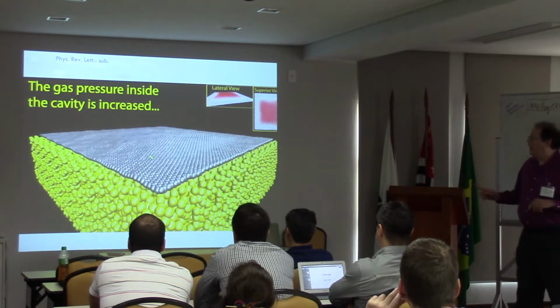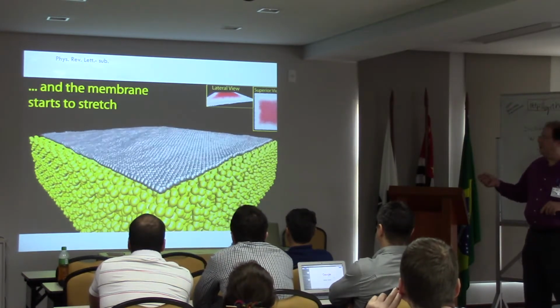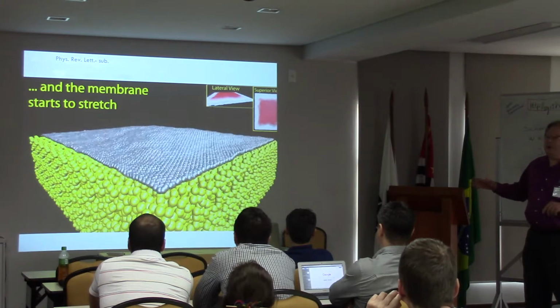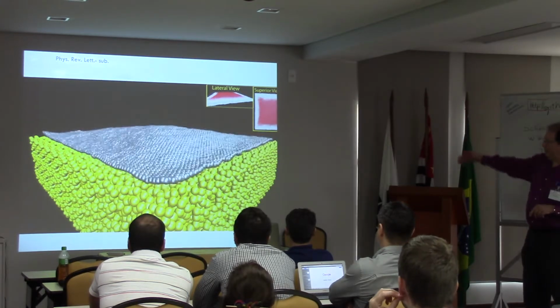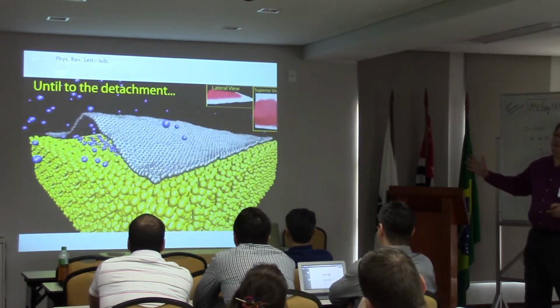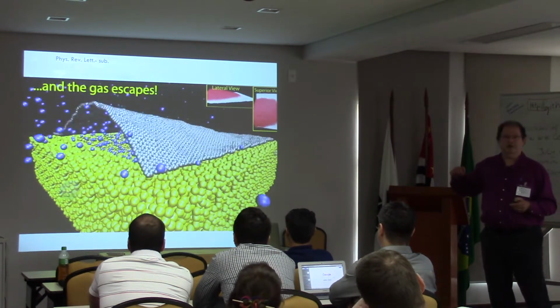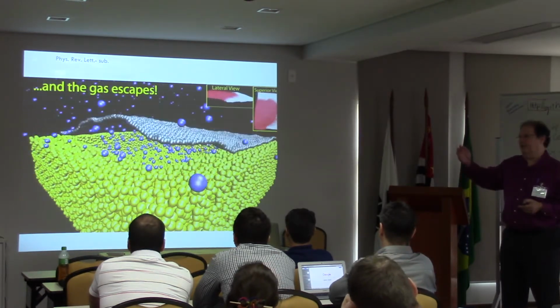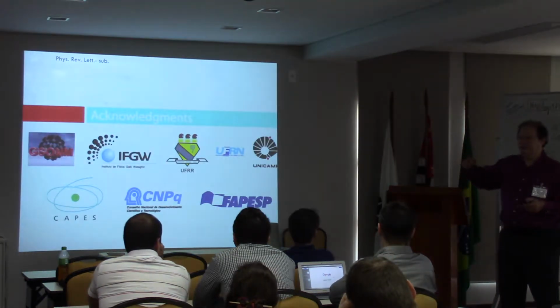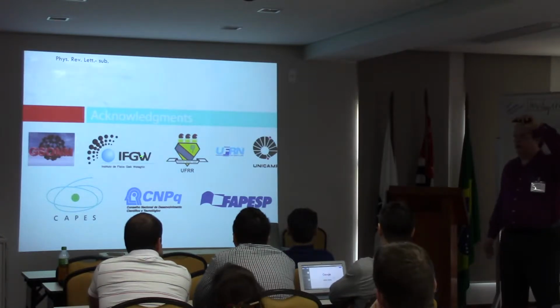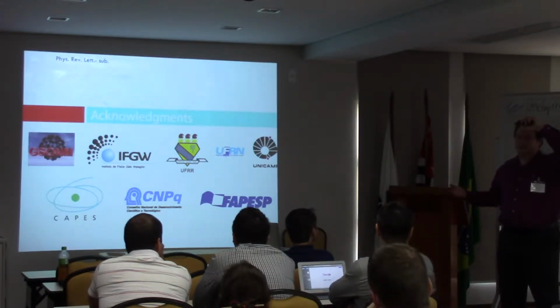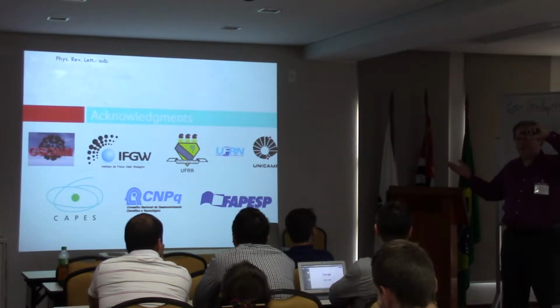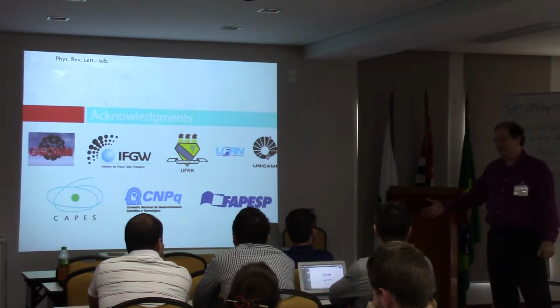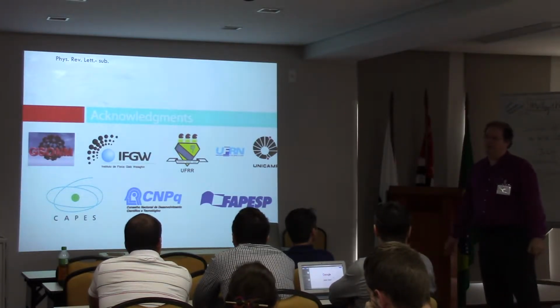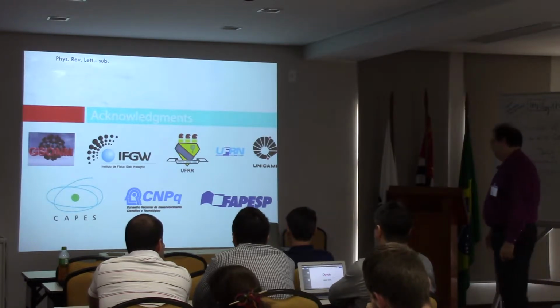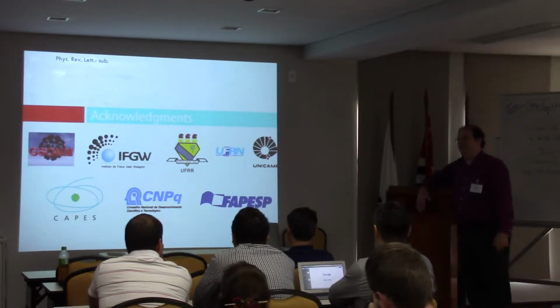The question, how is the detachment? If you have a small leakage, not good. But if you have a sudden detachment that you see in the simulation, see, that's very good. Why? Because this can be used as a sensor for gas or oil leakage. And you can use a very simple optical probe to measure the signal. Then you have a very effective sensor, which could be used in very harsh environments, and a low-cost material. We're trying to make this test in the real field.